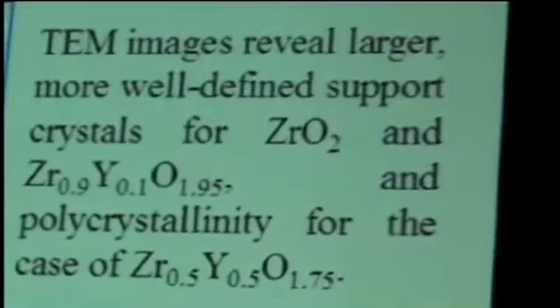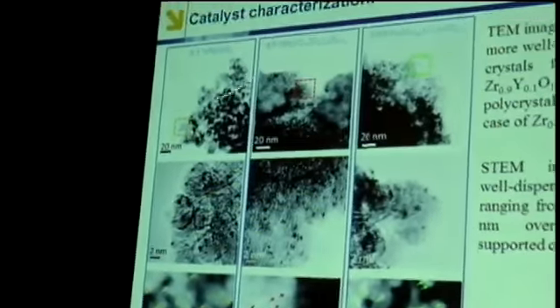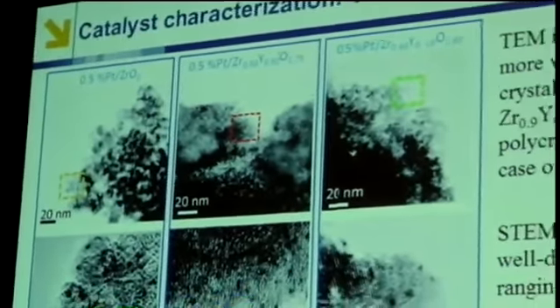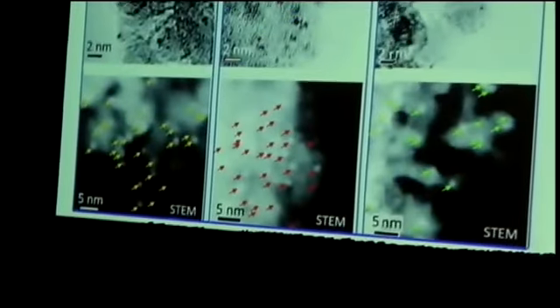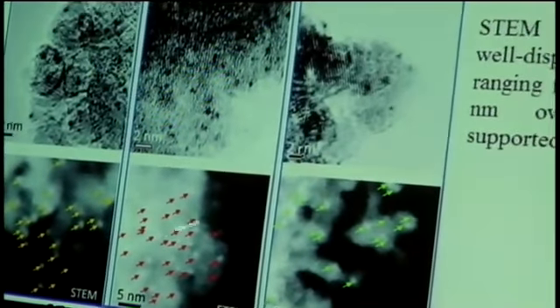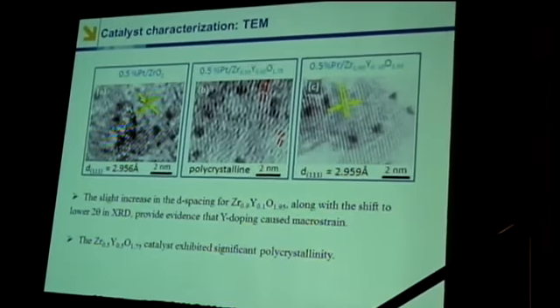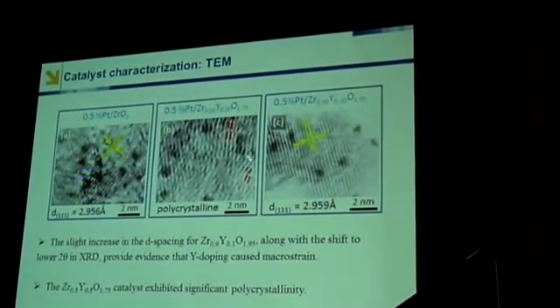We looked at TEM, and these images were taken by Dr. Rishi Graham. For the undoped and 10% doped, we had significant crystallinity, as the XRD showed. But for the 50% doped, there was significant polycrystallinity, also in agreement with the XRD. And the platinum particles ranged from about 0.5 nanometer to 3 nanometers over all three. Very small platinum clusters. And we also saw a slight increase in the d-spacing for the 10% doped zirconia catalyst, which is consistent with the shift to lower 2 theta that was observed in XRD. And here you can see the polycrystallinity in the 50% doped one. You can see it better here.